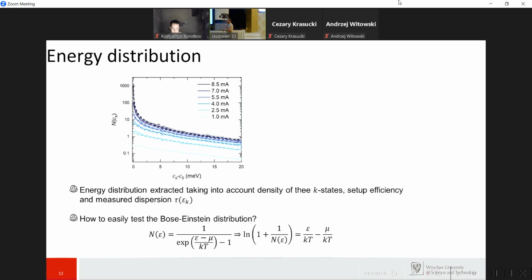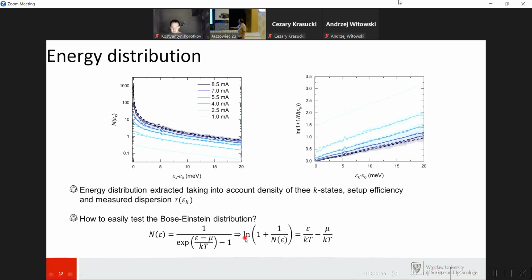You can easily test if your distribution is Bose-Einstein. You can rewrite this in a logarithmic form, simple algebra, and it should give a straight line. So we have straight lines, and you can see that the straight lines have different slopes. So that was a surprise to us, because it means that, as you see, the slope is related to temperature. So our condensate is there, but it has different temperatures.